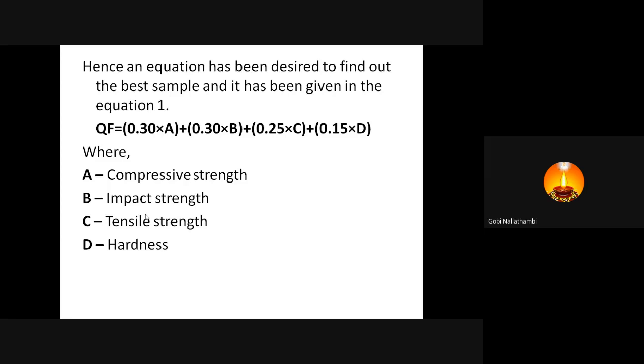So here the quality factor is derived by this equation. We can also change this weightage based on our requirement. It is not necessary to maintain the same value. Based on our application or utilization of the sample for a particular end use, that is the composite, we have to give the weightage for a particular property. So if, suppose, the sample is used where tensile strength is an important force acting on the sample, we can give higher weightage for tensile strength. Then we can modify this equation to get a quality factor.